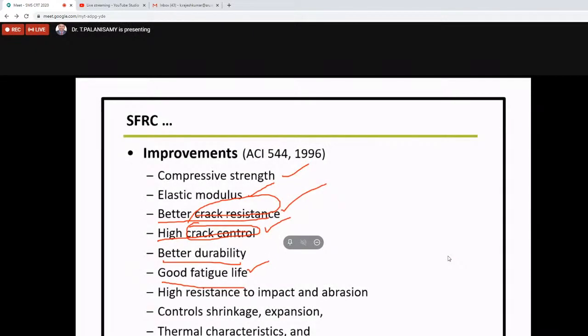It takes more time to fail the structures. So it controls the crack, and the propagation of the crack is also controlled. Then better durability, that is a common point. Good fatigue life. So if you apply fatigue load and add the fiber, it definitely improves the life of the structures. Then high resistance to impact and abrasion, this is also a valid point. It controls shrinkage and expansion. Thermal characteristics and better fire resistance.